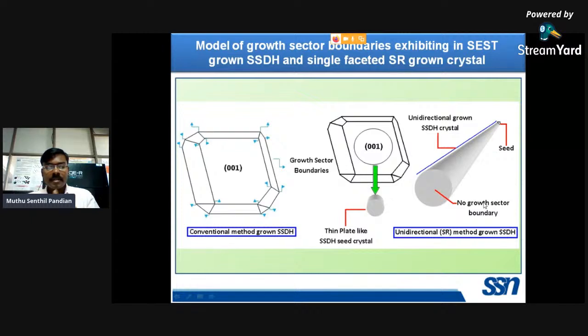But in the SR method, what we have done is we have mounted a single and morphologically defined facet. We mounted the seed crystals here at the bottom of the glass sample. With a single morphologically defined facet, there are no or fewer growth sector boundaries compared to the conventional method grown crystal. There are no micro inclusions and no milky opaque regions in the SR method grown crystal. So naturally, the mechanical stability, optical quality, and crystalline perfection of the SR method grown crystal are high, superior compared to the conventional method grown crystals. In the conventional method, you can see there are a lot of growth sector boundaries. It has been already reported that the dislocations originate from the growth sector boundaries. But in the case of SR method, there are fewer or no growth sector boundaries.